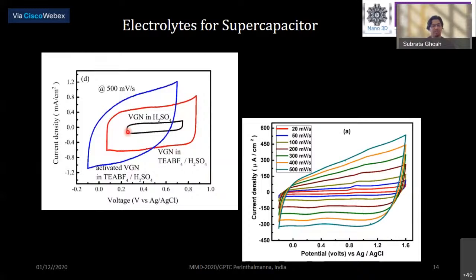You can see the window of this VGN is 0.15 to 0.75, so basically the window is 0.6. But for VGN in TEABF4 H2SO4, the window starts from 0.1 to 0.9, so the window is 0.8. So it is increased. Then, in this case, we did some activation of the VGN graphene, and explored the same electrolyte, which we named an organo-aqueous electrolyte, and here we see the window is increased to 0.9 volt.